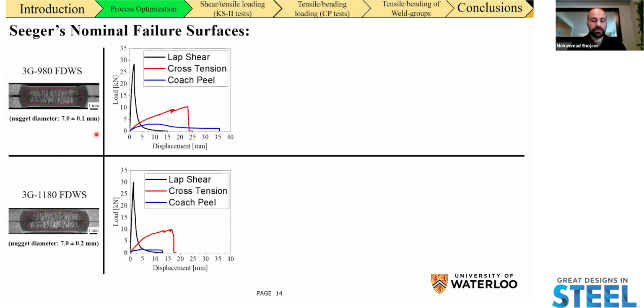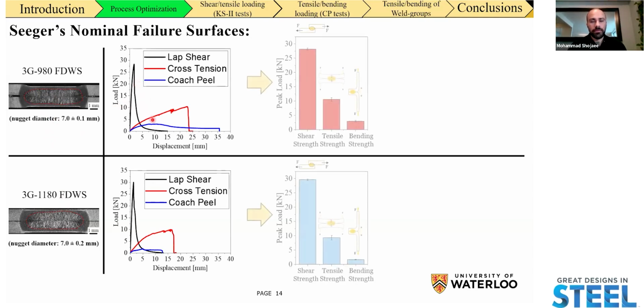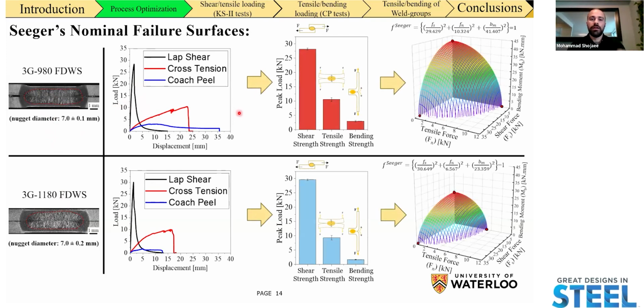We performed lap shear, cross tension, and coach peel tests. You see the representative load displacement curves for these tests. And from these, we extracted the peak load and constructed the 3D failure contour surface that was suggested by Seeger. Now, note that in the equation of these failure contours, the exponents are all equal to 2. That's traditionally accepted because we don't really have the data points to optimize these exponent values.